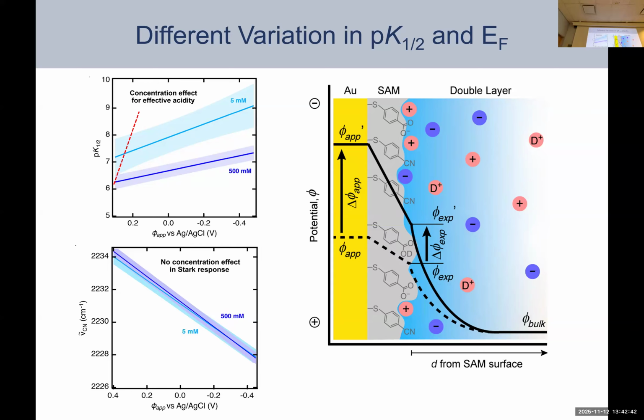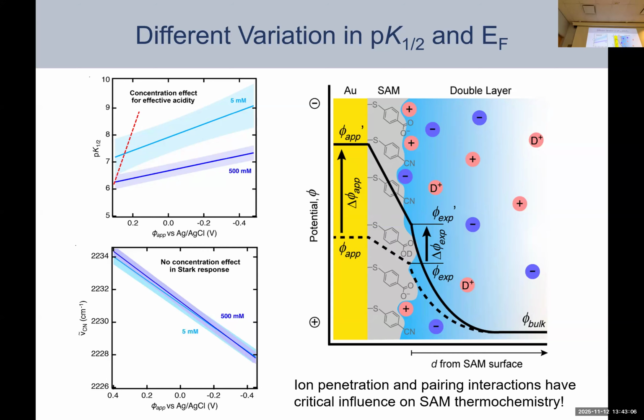In this case, the way we understand it is that there's a huge drop in potential as you go across this SAM interface, okay? And so the applied potential may be expected to be changing acidity by a 59 millivolt per decade relationship, but the experienced potential of where this carboxylic acid group is massively attenuated, okay? And essentially we believe that ion penetration, ion pairing, and solvation at this interface is dramatically screening what this carboxylic acid is experiencing, even at the molecular length scale away from the electrode.